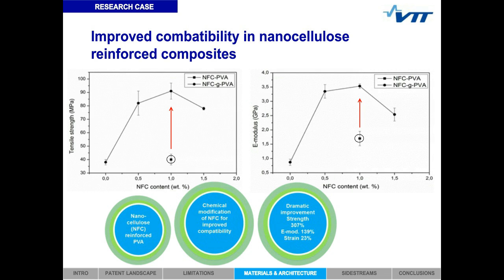In the figure on the left-hand side, you see the evolution of the tensile strength as a function of the nanocellulose content. As you see, when we had 1% of nanocellulose without any modification, there is hardly any improvement in tensile strength. However, with the same content, only 1% of nanocellulose, after the chemical modification, when the material is able to form a covalent cross-linking with PVA, we have improvement in strength. We have over 300% improvement in tensile strength.